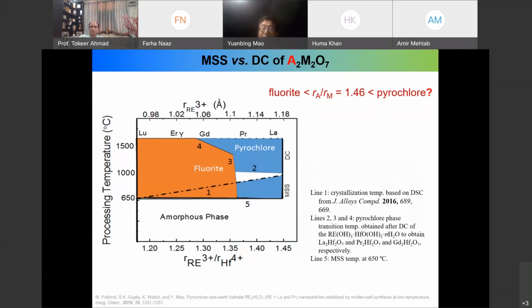So if we combine the results from these two synthesis processes, you will see that by the molten salt synthesis, for these two, the praseodymium and lanthanum hafnates, we already got the pyrochlore structure, even though the synthesis temperature is only 650. But for the other four, they are fluorite structure. And then for the direct calcination, for these two, only after a temperature of 1,000 degrees by direct calcination do we get the pyrochlore. But for this one, we can convert it at high temperature into the pyrochlore structure. So that tells us how these two combine together. That's related to the synthesis.